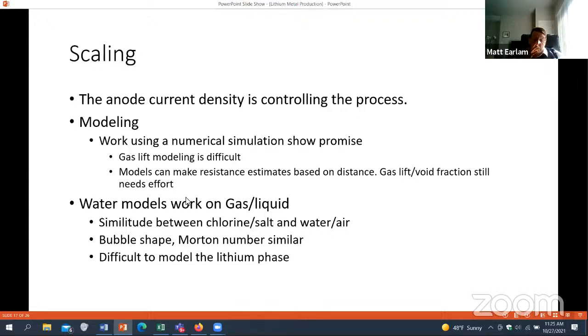Water models is what we worked on about 2 years ago. There's really good similitude between water and air and chlorine and salt. So you can do a pretty good physical model. The bubble shapes and sizes and rate of rise between chlorine and salt and water and air are about the same, because the Morton numbers used to describe that flow are very similar. But it's really difficult to model the lithium phase because of the fact that the density difference is so high between the salt and the metal, almost 1 gram per cc. It's very difficult to find a model for lithium that will represent lithium properly.